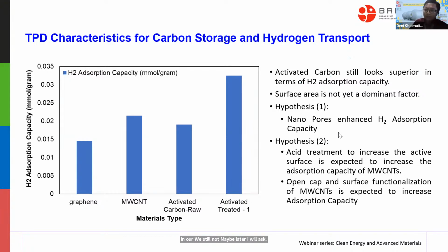We have two hypotheses here. First, nanopores enhance the hydrogen adsorption capacity. In hypothesis number 2, the acid treatment to increase the active surface is expected to increase the adsorption capacity of MWCNTs, and open cap and surface functionalization of MWCNTs is to increase adsorption capacity. I think this is just the carbon one, right? So we need to enhance the surface area or the pore size, I mean the pore distribution, with a certain pore diameter.